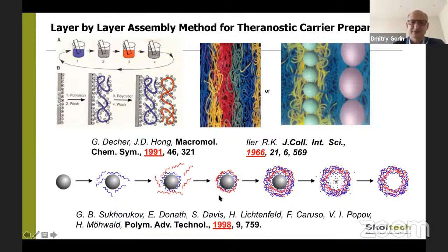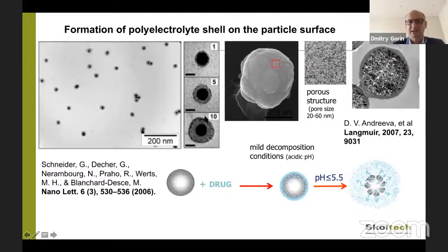the last century, one group that was working at this time at the Max Planck Institute of Colloids and Interface Science suggested using, instead of a planar substrate, the surface of particles, and they formed core-shell particles using this technology, and hollow shells after dissolving of the core. And using this technology, we can form the shell on the surface of inorganic nanoparticles, for example, gold nanoparticles with a polymeric shell. But in our lab, we used a polymorph modification of calcium carbonate named vaterite. Why vaterite? Because the vaterite particles have a porous structure, and also we can dissolve these particles in mild conditions.